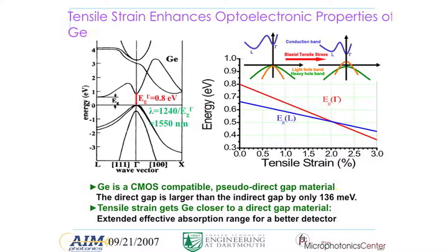In terms of band structure, textbooks say germanium is an indirect-gap semiconductor, meaning photon absorption requires matching momentum at the L-valley in the [111] direction — the body diagonal of the cubic lattice — which is usually inefficient. But if you look at the direct transition, germanium has a direct gap of about 0.8 eV. A quick calculation shows that corresponds to 1550 nm, which is basically the telecom wavelength we're interested in. By utilizing this direct-gap transition, we can greatly benefit from the very efficient absorption of germanium.